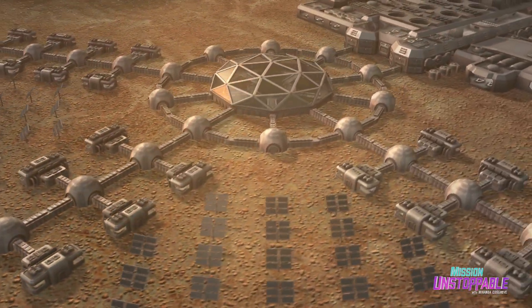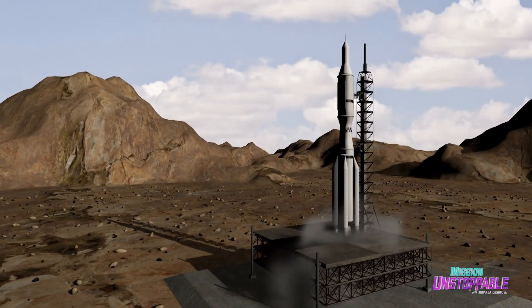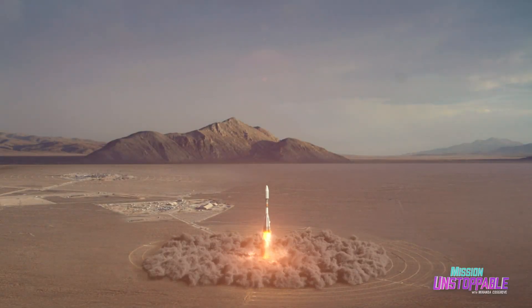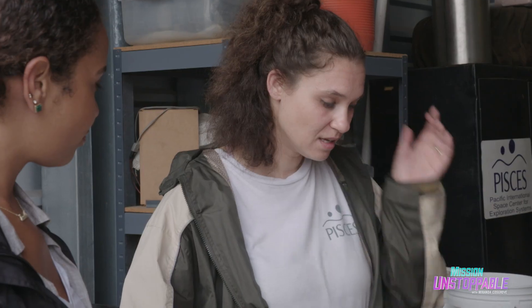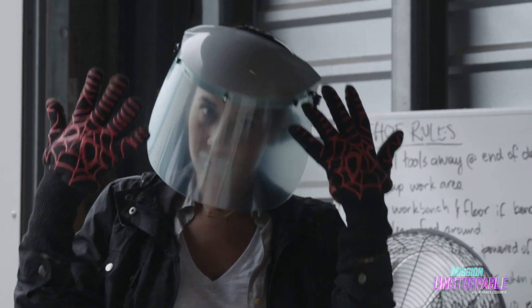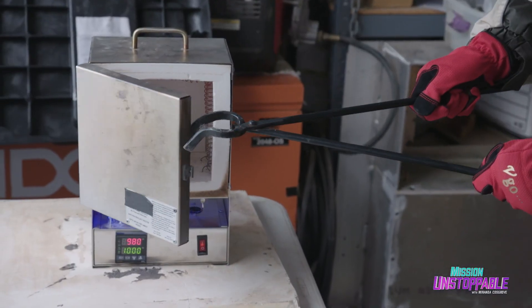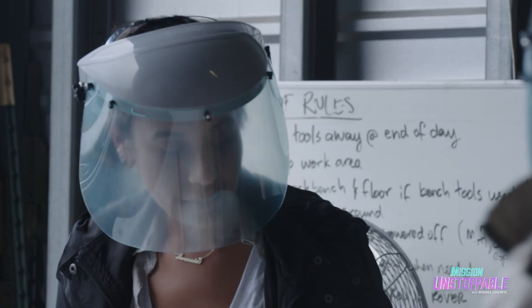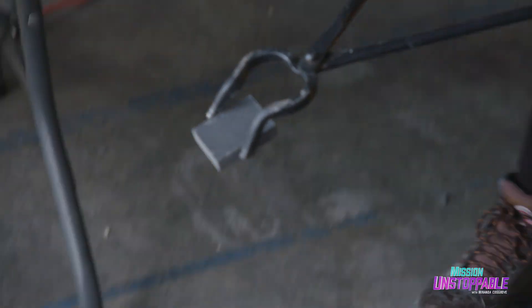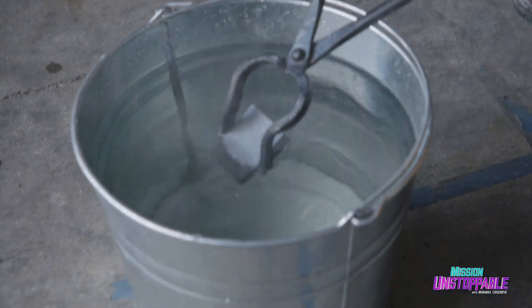Another cool part of Kyla's job is the thermal shock test. Her materials will be used in everything from habitation pods to launch pads — they need to endure below-freezing temperatures and withstand the scorching heat of a rocket engine. Thermal shock is basically heating up the material really super hot, then dunking it into cold water to see if it'll crack or break. Kyla uses tongs since the kiln is so hot. This chunk of material is an incredible 1,000 degrees, and once dunked in cold water, it survives the test without so much as a crack.